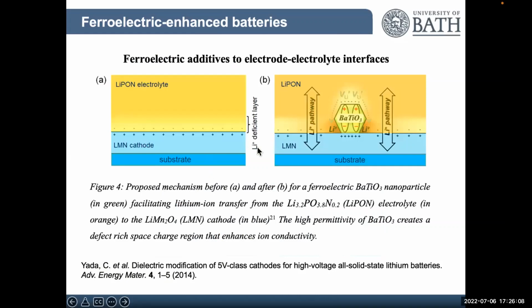Again, it's not our work, where the barium titanate ferroelectric has been added as an electrolyte interface. And so that high permittivity region produces defect-rich regions, which affects the lithium plus pathway and enhances the conduction. So again, I think there's interest there in using really the high permittivity properties of these materials in battery systems. And there's also some other work where it claims to be using the piezoelectric properties to enhance batteries as well.